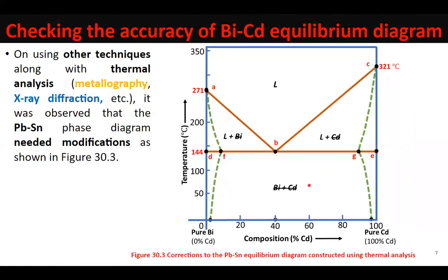So students, when we went back, we saw that we had made an assumption that there are two elements which are very different, but they are still showing 100% liquid solubility. Now the point is that these systems might be disobeying the Hume-Rothery rules for the formation of solid solutions to an extent. But if these are showing 100% liquid solubility, that's a great thing. They can show less solid solubility, but they cannot show zero solid solubility.